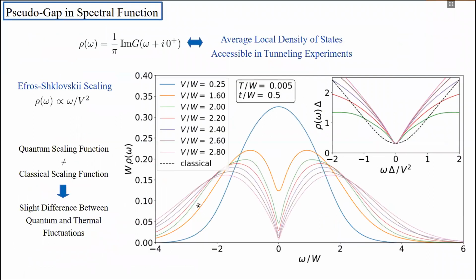So just very briefly, we got this pseudogap behavior and there's this local Hartree distribution, but that might seem like an artificial object to you. But instead, we can recover the same scaling function by examining the density of states, which is also experimentally accessible in tunneling experiments. So we get a similar Efros-Shklovskii scaling. Rho omega at small omega is just proportional to omega divided by V squared. This scaling collapse is shown on this figure. So the main figure shows just the density of states at different interaction strengths, and the scaling collapse is shown here in the inset.